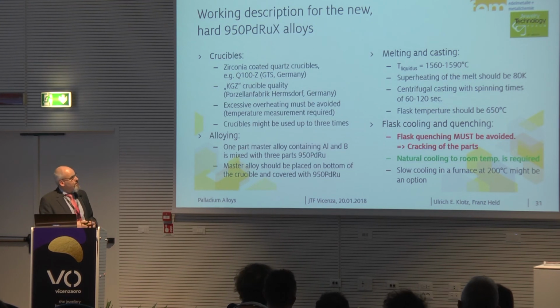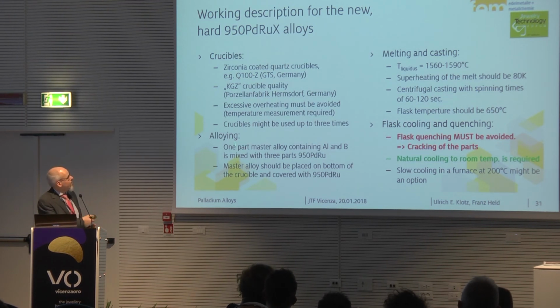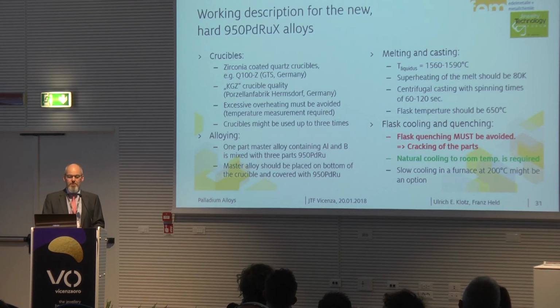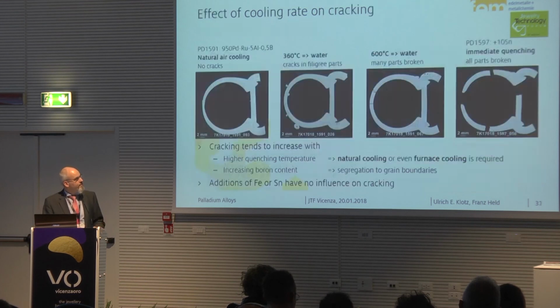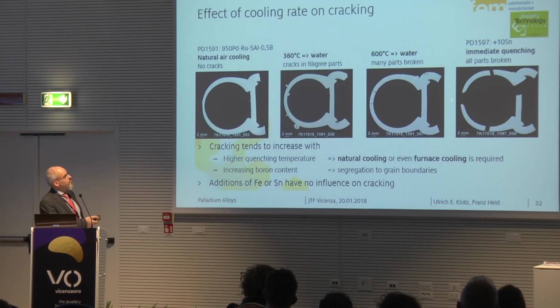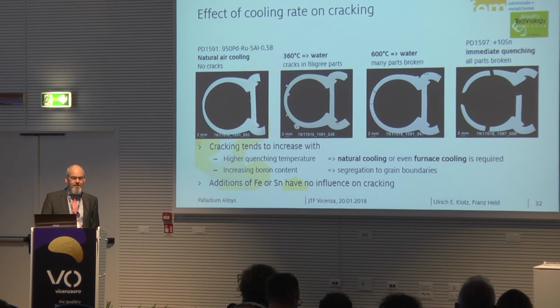However, you have to keep some points in mind. I don't go into detail through this list of how to work with these alloys, but you have to keep in mind one point. This is the flask quenching. Usually after casting, you leave the flask for some time in the casting machine to cool down. And this is very important for these palladium alloys. This is demonstrated here. If you take out a flask immediately after casting and quench it, all the parts are broken. So this is, of course, not good. So we have to take care of this point.